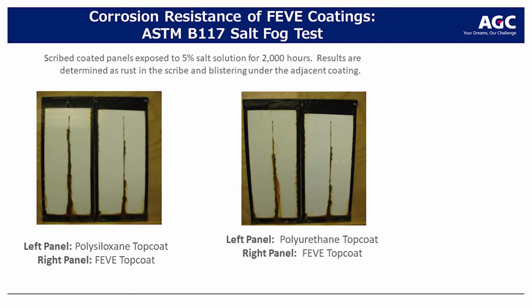In this particular case, they're looking at a polyurethane and a polysiloxane. Visually, you can see there's less rust in the scribe from the FEVE coating than there is in the urethane and the polysiloxane. They did not look at movement under the scribe or blistering under the scribe in this particular test.